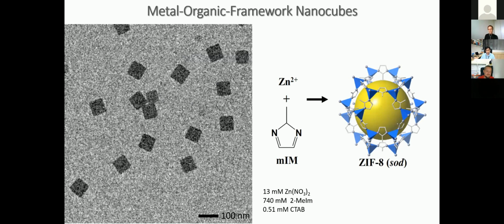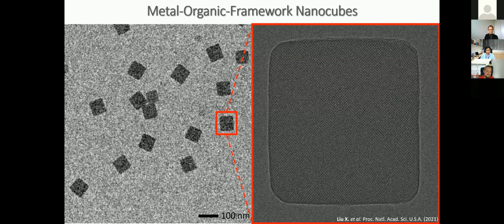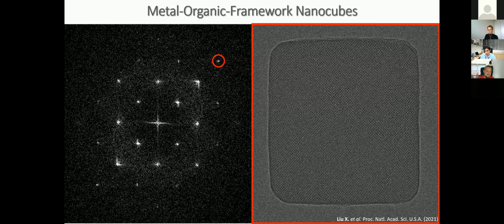So to really identify how this nucleation happens, what we did was synthesize cubic MOFs. For these MOF crystals, you just add a trace amount of CTAB, and all of a sudden the MOF crystals you're synthesizing become cubic MOFs. And these MOFs are highly crystalline. They're single crystals; you can see it from this Fourier transform pattern. We're going to use the shape as a signature of crystallinity, because when we're doing in situ, we're not going to be able to see the lattice resolution. So our goal is to use the shape. If you have a cubic shape, then it's a crystal.